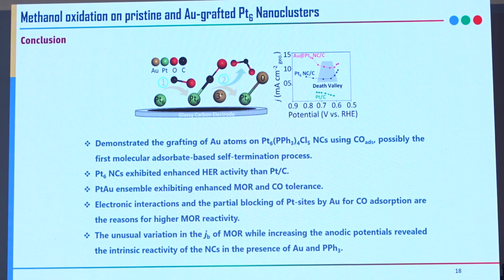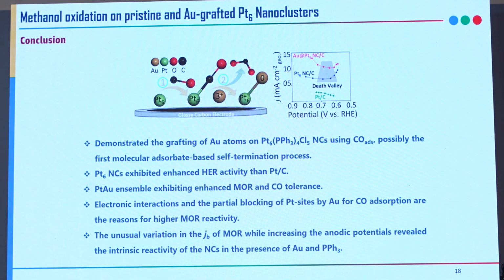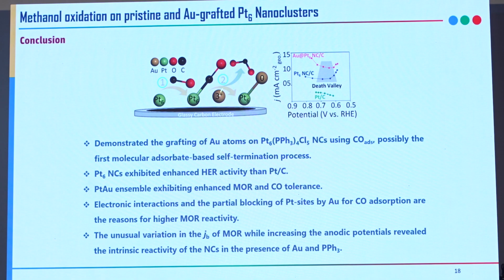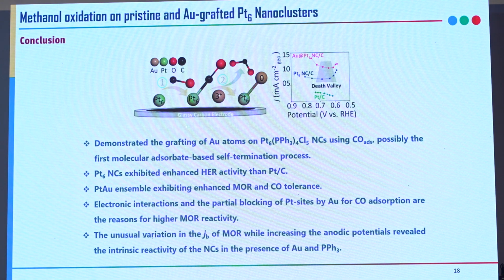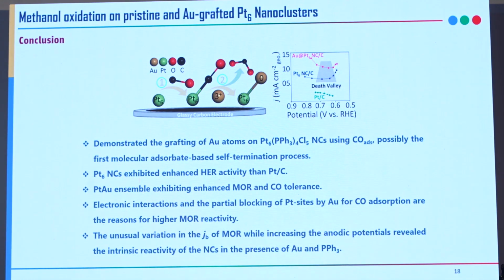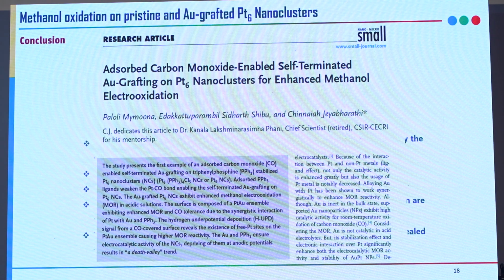So in conclusion, we prepared PT6 nanoclusters, triphenyl phosphine stabilized PT6 nanoclusters, and we decorated Au atoms using the adsorbed CO for the decoration of these Au atoms, which we used for enhanced methanol oxidation with better CO tolerance. And this work we published in Small.